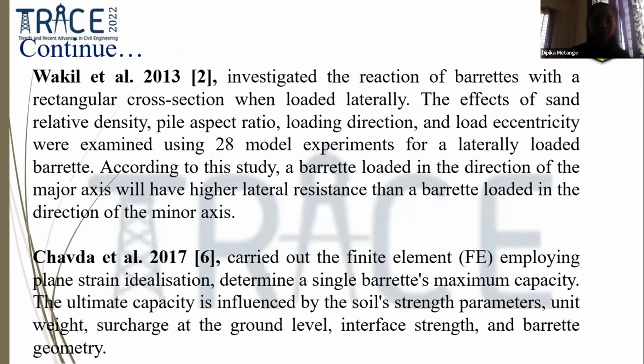Now, the next literature is by Wakil and others. In 2013, they investigated the response of barrettes with rectangular cross section when loaded laterally. The effects of sand relative density, pile aspect ratio, loading direction, and load eccentricity were examined using 28 model experiments on laterally loaded barrettes. According to their study, a barrette loaded in the direction of the major axis will have higher lateral resistance than a barrette loaded in the direction of the minor axis.